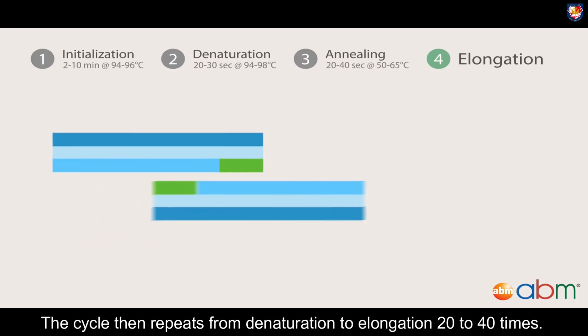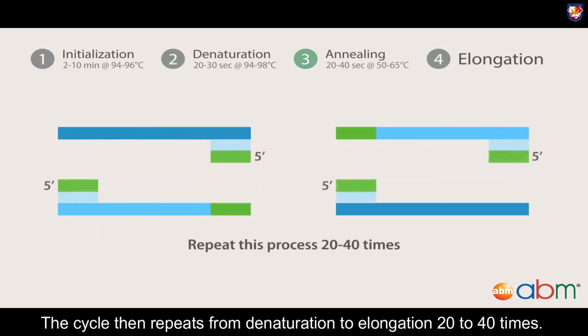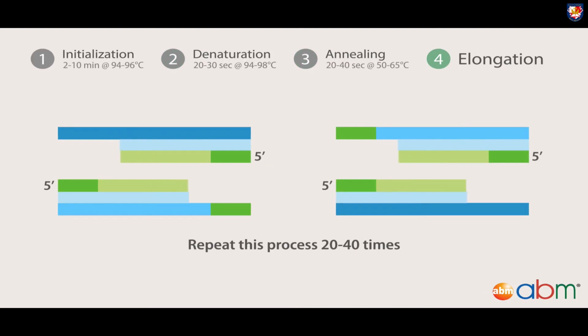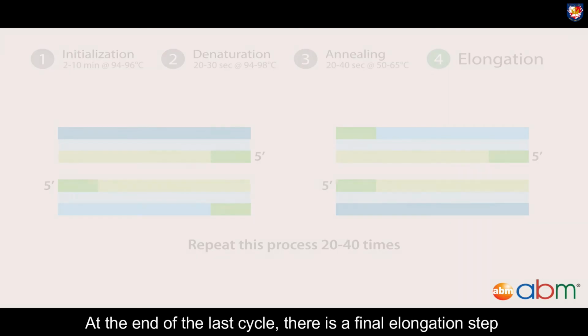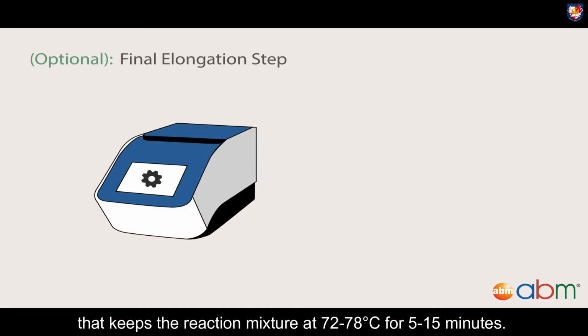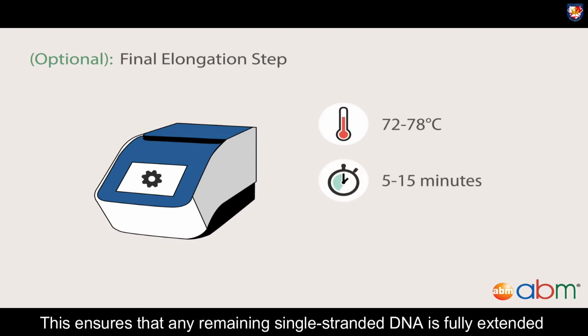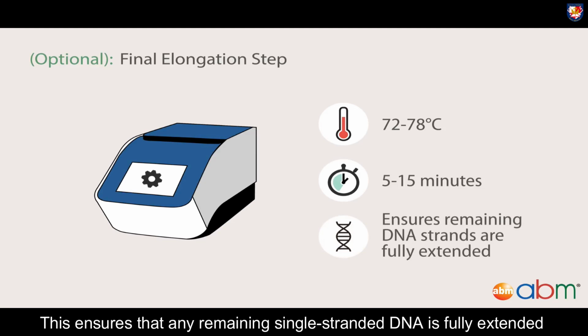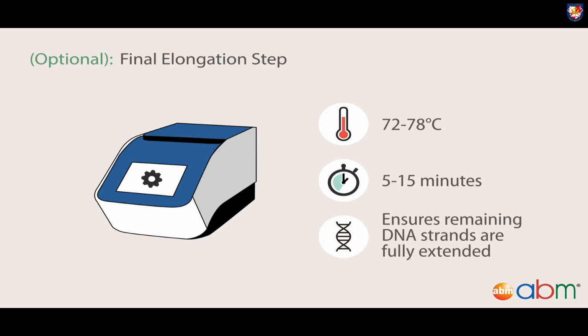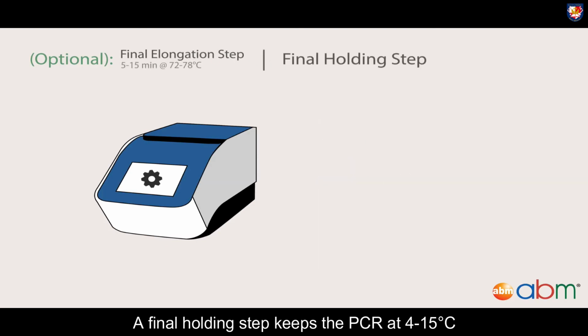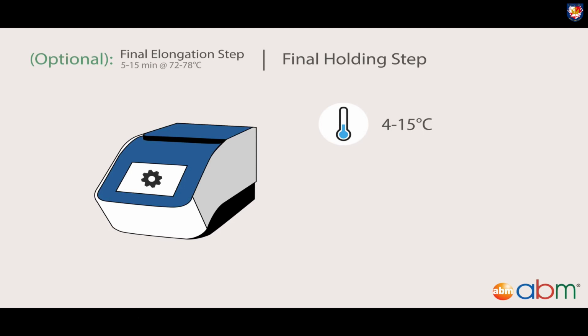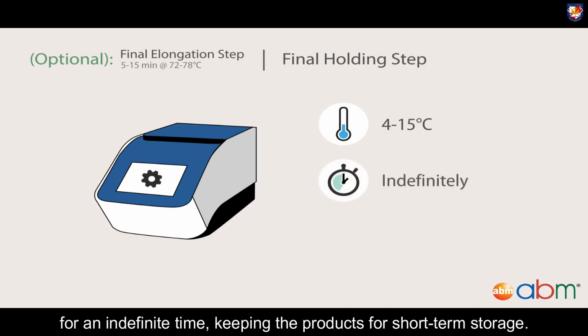The cycle then repeats from denaturation to elongation 20 to 40 times. At the end of the last cycle, there is a final elongation step that keeps the reaction mixture at 72 to 78 degrees Celsius for 5 to 15 minutes. This ensures that any remaining single-stranded DNA is fully extended after the last PCR cycle. A final holding step keeps the PCR at 4 to 15 degrees Celsius for an indefinite time, keeping the products for short-term storage.